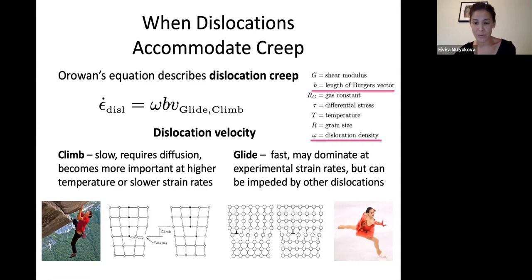So each of these processes has its own characteristic time scale that, for your intuition, I'm characterizing with a climber and a glider. Climb is typically slower. And one of the reasons it is slower is that this type of dislocation motion requires diffusion of vacancies across the grain. So this is a diffusion limited process. As with any diffusional process, it becomes more efficient at higher temperatures. And also, just because it's happening slower, when your rock is deforming at a slower rate, climb may become increasingly more significant as to how much it contributes to the overall deformation.